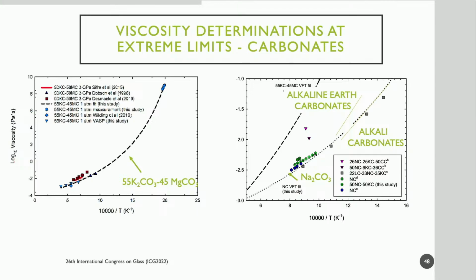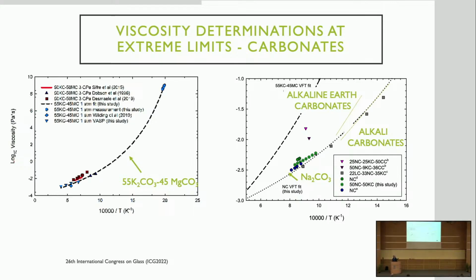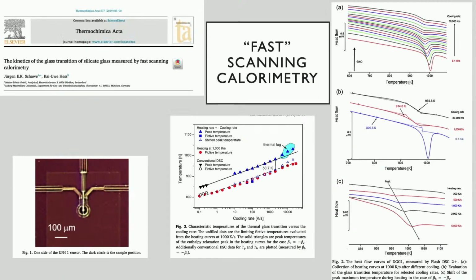And another area where we've done a lot of this kind of work is in carbonate liquids. You can actually make glasses out of carbonates. This was speculated about 100 years ago. It was observed 50 years ago, and the glass transition was determined just a few years ago. For the first time ever in physical chemistry, the glass transition of a carbonate glass was determined. And that glass transition allows us to pull these data points off of a calorimetric curve and to complete the curve for the temperature dependence of the viscosity of a carbonate liquid, which, as you can see, is highly, highly non-Arrhenian.